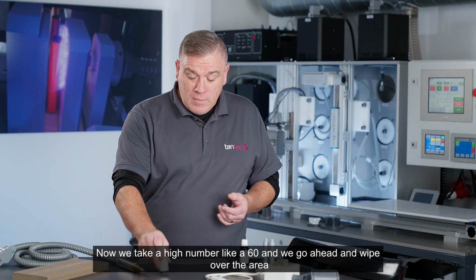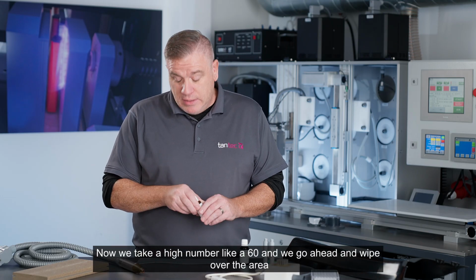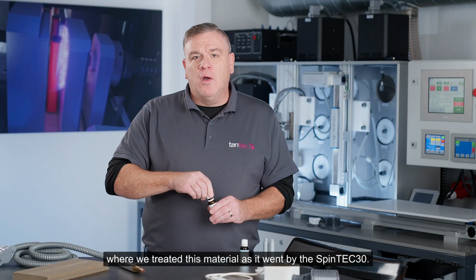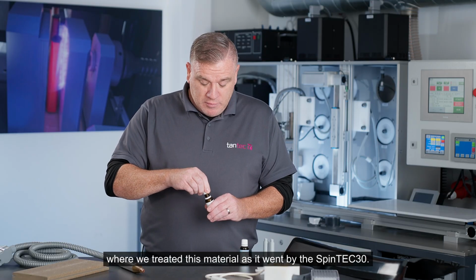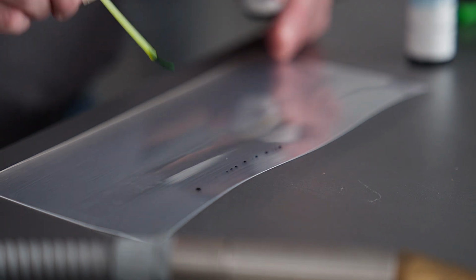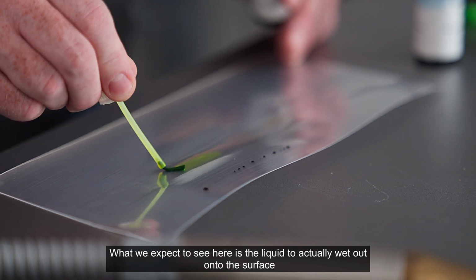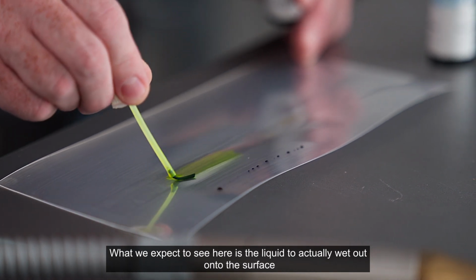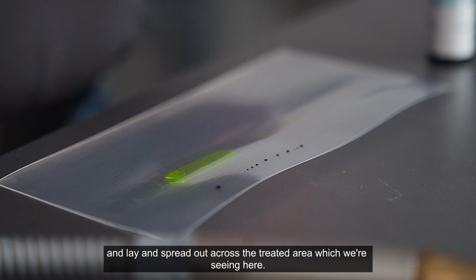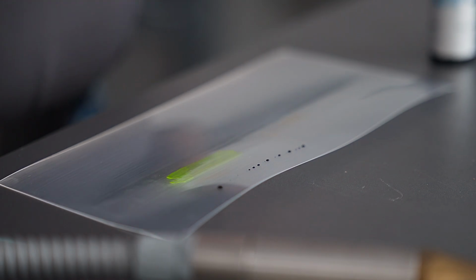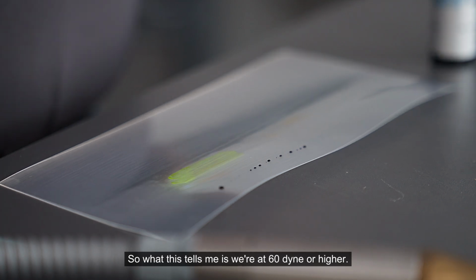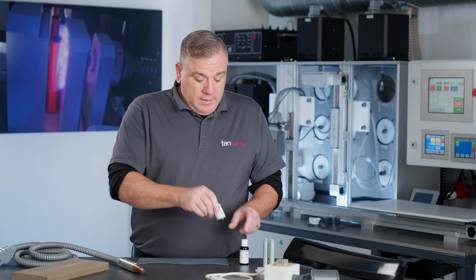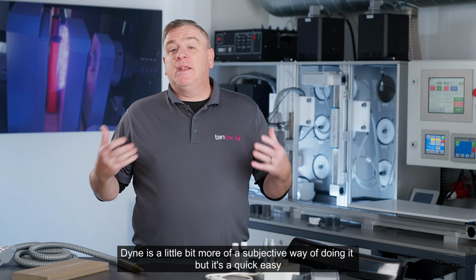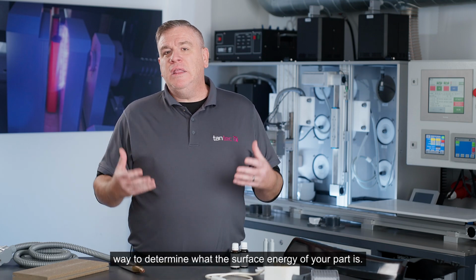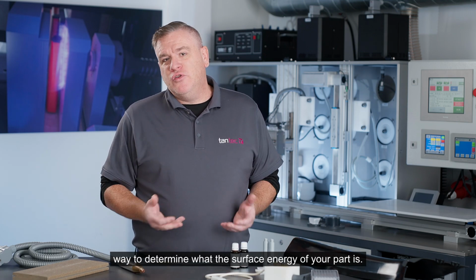Now we go ahead and take a high number like a 60 and we wipe over the area where we treated this material as it went by the SpinTEC30. And what we expect to see here is the liquid to actually wet out onto the surface and spread out across the treated area, which we're seeing here. So what this tells me is we're at 60 dyne or higher. Dyne is a little bit more of a subjective way of doing it, but it's a quick, easy way to determine what the surface energy of your part is.